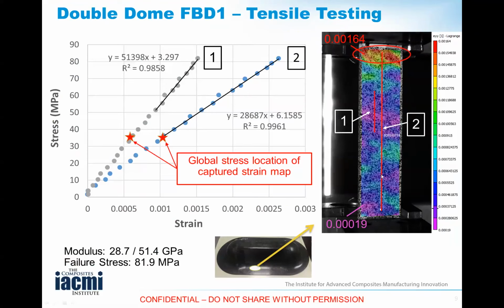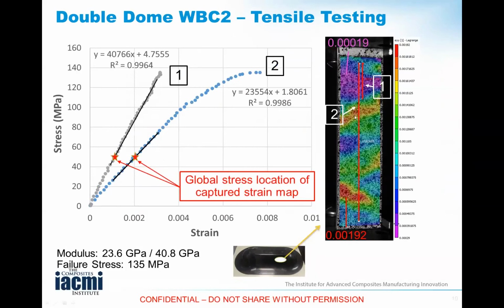What you see is there's a tremendous localization of strains, and these are measured with three-dimensional surface digital image correlation-based techniques. If I use this as a strain gauge, that gives you the stress strain curve there, showing a modulus of 51 gigapascal. If I use the entire gauge length, which is typically what you would use, for example a large extensometer, then you would get a stress strain curve showing a modulus of 28 GPa. So a lot of the traditional mechanical testing techniques are no longer valid. To interpret them correctly, one has to account for these local variations, largely resulting from fiber orientation and matrix-rich regions.